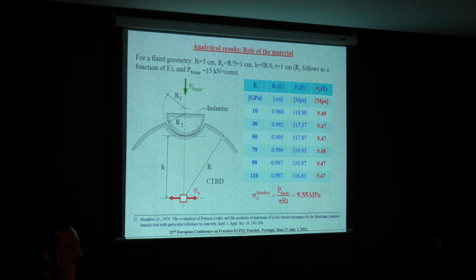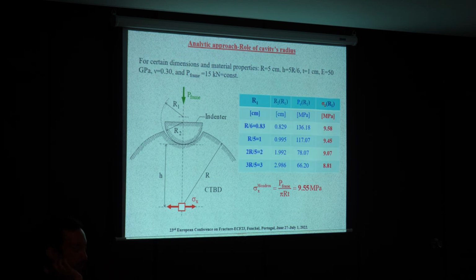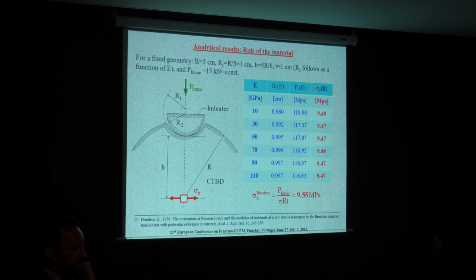Okay, you can see the role of the material here. As I mentioned, using this technique, the material does not play any significant role. And the values obtained for the tensile stress, I do not say strength, because we are not sure that this parameter is the tensile strength, are very close to that proposed by Kourkoulis, if this is the tensile strength of the material. Who knows? Moreover, we have tried to determine some optimum geometrical parameters, because we would like to propose this as a standard: the radius of the hole, the radius of the indenter, the distance of the indenter. You can see that there are some combinations for which the results are very close to the results proposed by Carneiro, Akazawa, and Kourkoulis, very close to this 9.5 megapascals.